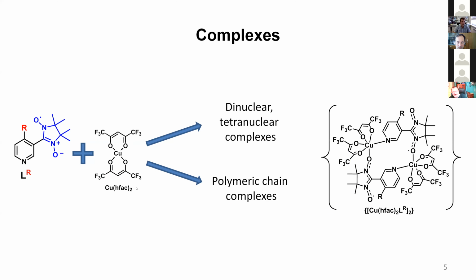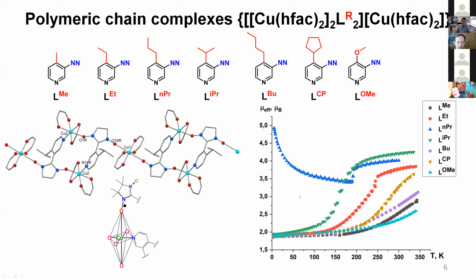Its reaction with copper gave a variety of molecular, dinuclear, and tetranuclear complexes, and polymeric chain heterospin complexes with an analogous binuclear cyclic fragment for all compounds. I will start from the polymeric chain complexes obtained for the following nitroxides. The solid phase consists of centrosymmetric binuclear fragments bonded by copper bischelates into a polymeric chain. When the cooling-heating cycles are repeated in the temperature range from 5 to 350 Kelvin, a reversible spin transition takes place.